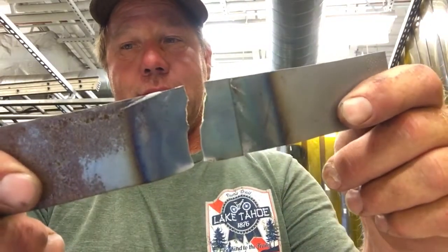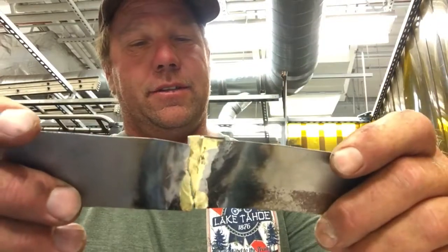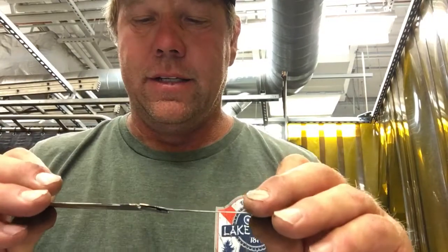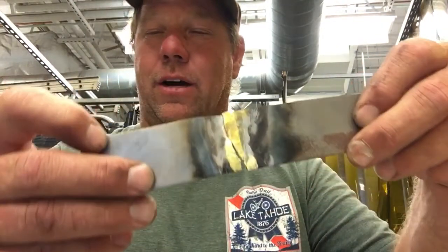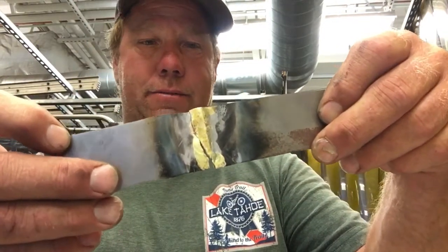I did that on some thinner stuff. And you can see a little too much heat. You can actually see that from the rainbow on the back, just how far I got that heat to go. A little too far. So this is more of that heat affected zone. I'm guessing I got a little too hot with brazing. I probably caused a little bit of melting of the base material. Fails at the weld.